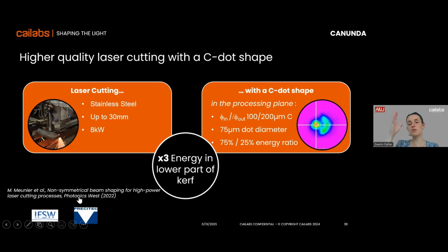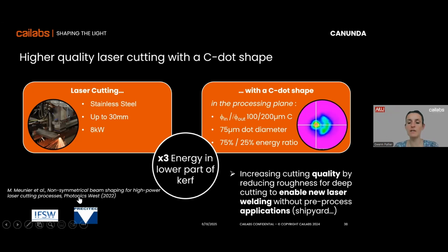So when you manage to optimize the energy all along the cutting curve, somehow what you can do is that you can remove post-processing. And it's super important because the whole idea is that you're cutting those parts because you want to weld them after. And if you can avoid the pre-processing application, you are saving a lot of time. So beam shaping, in order to optimize the energy through a 30 millimeter stainless steel cutting application.